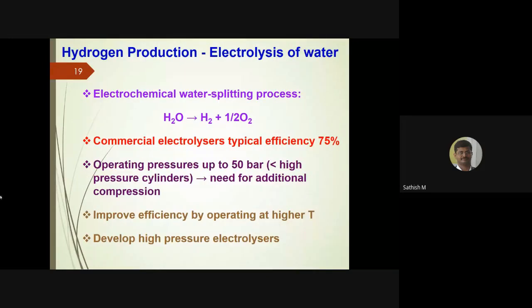So this is the electrochemical water splitting process. Water is split into hydrogen and oxygen. Commercial electrolysis typically has 75% efficiency. The operating pressure is up to 50 bar. That's less than high pressure cylinders, so additional compression is needed. The lower efficiency can be improved by operating at high temperature.